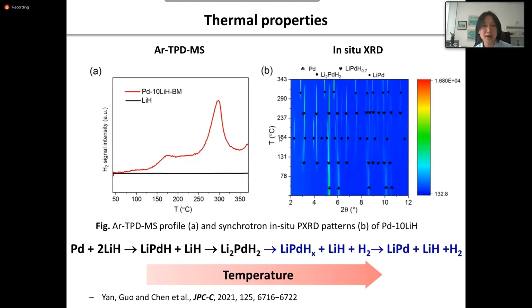Well, we use lithium hydride and palladium. We mix them together, and we heat the mixture without hydrogen pressure until a temperature above 350 degrees Celsius. We saw some transitions. At a temperature around 130, we saw the formation of LiPdH. We can regard this as an interstitial hydride. But at a higher temperature, around 180, we see the formation of the complex hydride Li2PdH2.